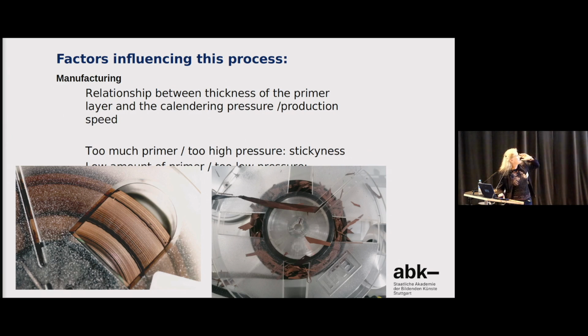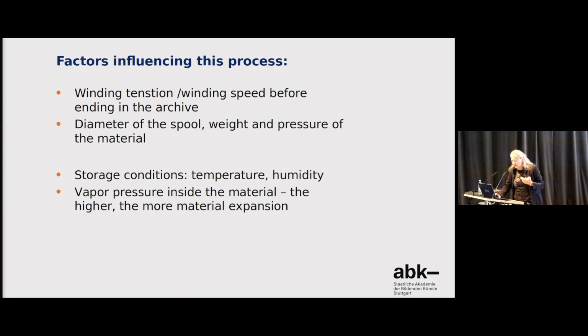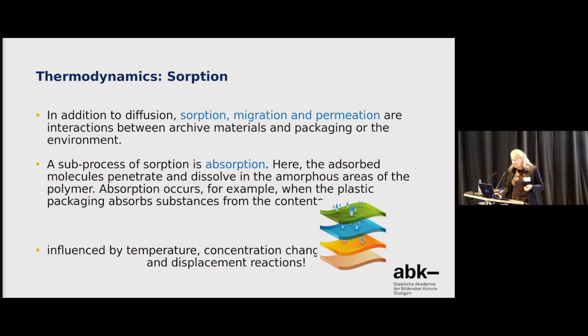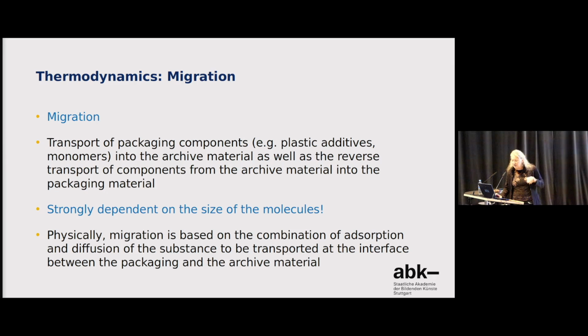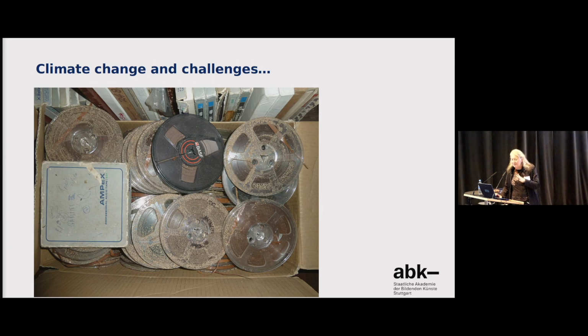So factors influencing this process is the relationship between thickness of the primer layer and the calendering pressure and also the production speed. They wanted to make it faster and faster and faster, and therefore this alignment was not done as correctly as it could have been done. And then you have two effects. One is stickiness, and the other is the contrary. You lose the information completely because it is not pressed hard enough together, or due to your storage situation you have these problems. So winding tension, winding speed before ending in the archive, diameter of the spool, weight and pressure of the material, storage conditions, temperature, humidity, the vapor pressure inside the material, the higher, the more material expansion. So all these thermodynamic factors lead to migration.